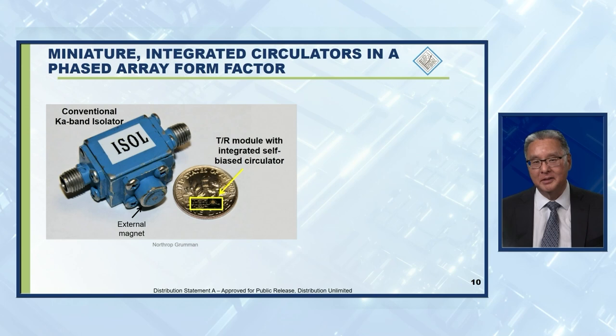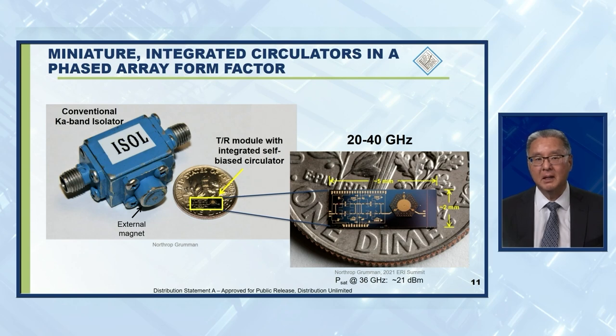In the photo, the MMIC outlined in yellow and sitting on a dime to provide scale demonstrates full integration of the self-biased hexaferrite circulator in the Ka-band TR module. For comparison, a connectorized Ka-band isolator is shown on the left. And in this expanded photo, you can see the circulator, that's the circle on the hexagonal plate, integrated with the gallium arsenide TR circuit. The module demonstrated 20 to 40 gigahertz performance with a saturated power of over 125 milliwatts at 36 gigahertz. And the 5 millimeter by 2 millimeter size is compatible with the requirements for the phased array.